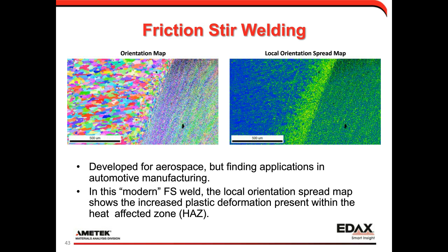I put a quote-unquote modern, or at least a more developed, friction stir weld to show the orientation map there on the left. The base metal transitions much more quickly into the heat-affected zone of the material. We also can use that local orientation spread map to see the amount of deformation present at the weld interface in the weld.